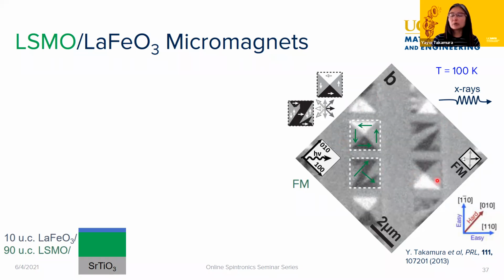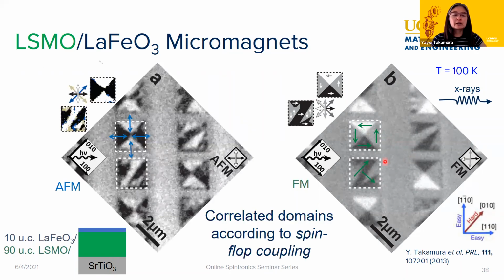This one down in the bottom right is still a Landau, but the core is shifted. And then we get these other interesting structures, which we kept calling Zorro domains because they look like the letter Z. These are ferromagnetic domains. So something is changing in our ferromagnetic layer because we have this antiferromagnetic layer directly on top of it. Then we could tune to the iron absorption edge, change to linearly polarized X-rays, and look at the domains that we get in the antiferromagnetic layer. And you can see that they basically map one-to-one.